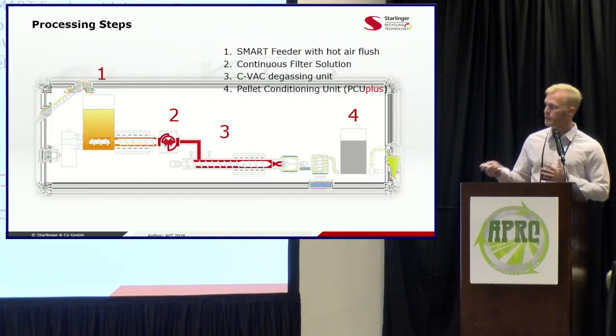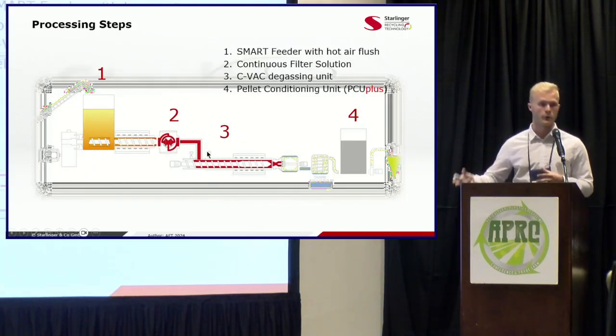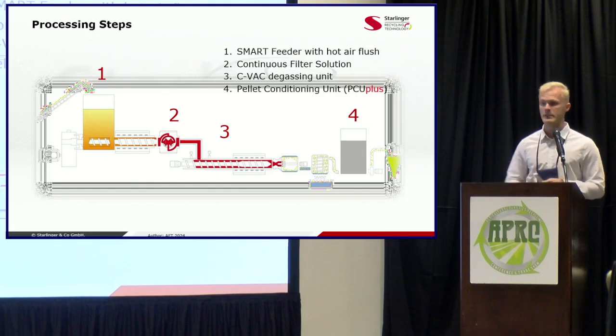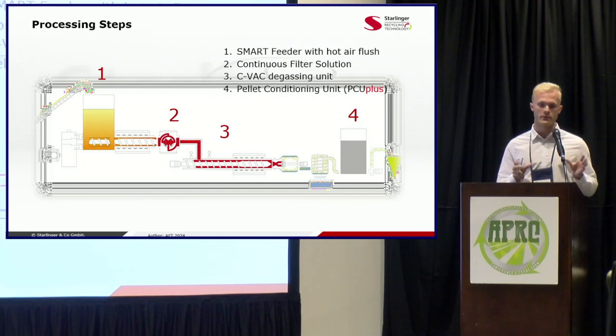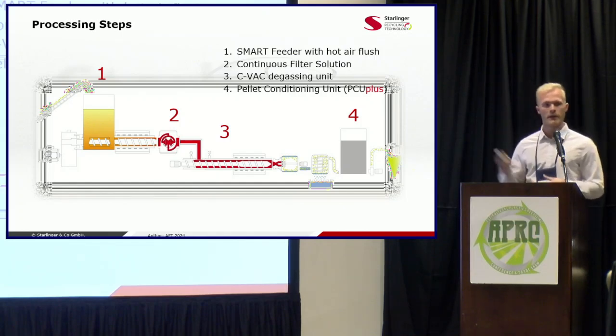But with our solution, we have the CVAC degassing second extruder after the first melt filtration step. And this is the most robust degassing system on the market, and it really opens up the melt with 2 vacuum systems before and after the point of entry to drive off those VOCs. And I actually have some GC data from gas chromatography that shows the initial reduction in VOCs from just the CVAC unit itself. And then, of course, comes the pelletizer.